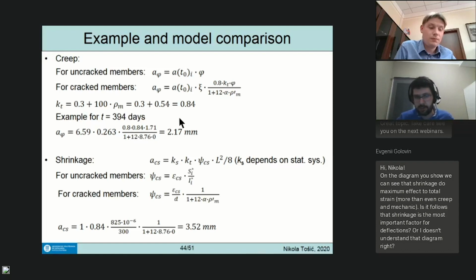And here you see it too, 3.52 versus 2.17 from creep. But this is just in this case, so it's not a generalization. Of course, for slabs, for buildings, shrinkage and the cracking it can cause is going to be a very important factor whose importance can be overlooked sometimes, I agree.